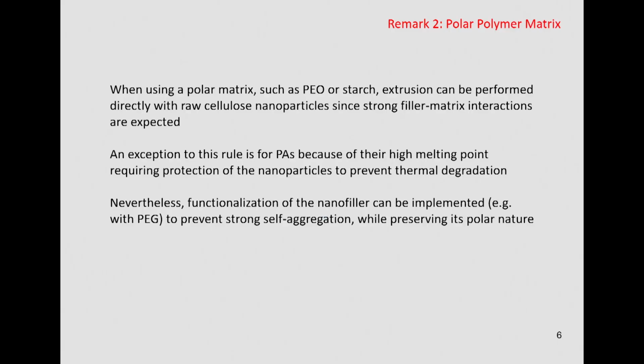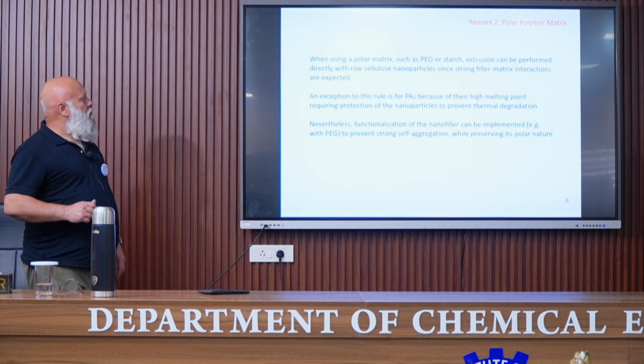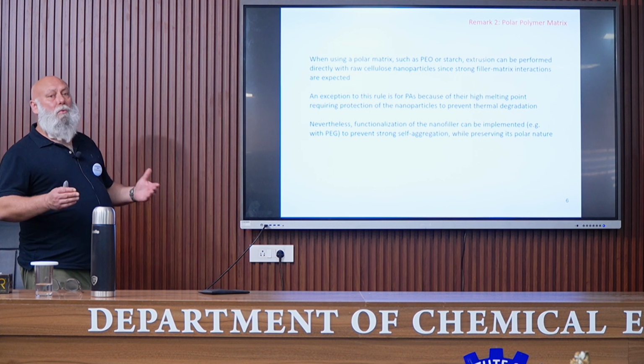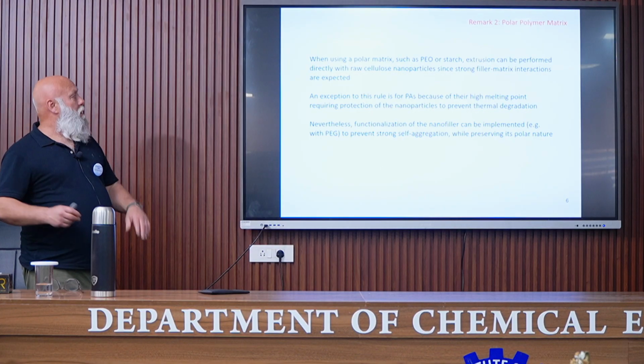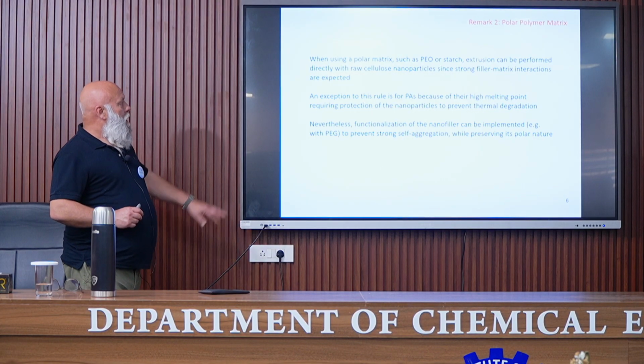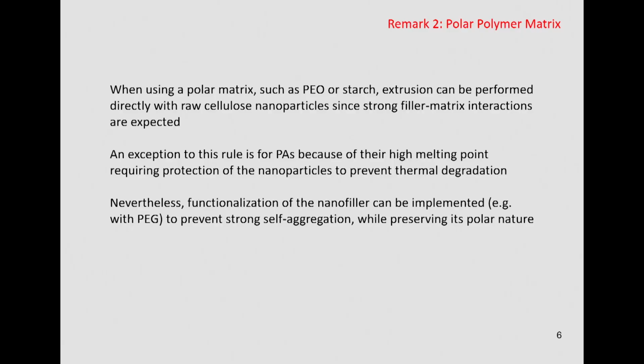Second remark regarding the polarity of the matrix. When using a polar matrix, which is the case for polyethylene oxide, for starch also, extrusion can be performed directly with raw cellulose nanoparticles, and we can expect strong interaction because both the matrix and the filler are hydrophilic. An exception to this rule is polyamides, because their melting point is high, and so it's necessary to protect the cellulose nanoparticles from thermal degradation. But even in the case of a polar matrix, functionalization of the nanoparticle can be implemented, for example, with polyethylene glycol, because it prevents the self-aggregation of the nanoparticles.